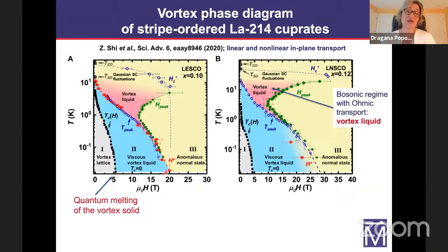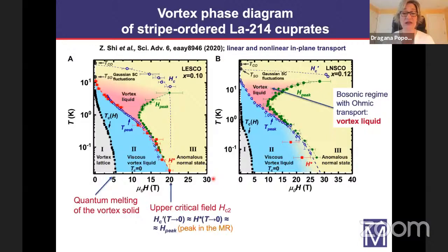So what we see here also is that all these different energy scales coincide, and it seems that this field here, 20 Tesla in this material, corresponds to the upper critical field. This is where superconductivity with vortices vanishes. We also looked at the magnetoresistance at high temperatures in a standard way, and these open dots represent the onset of Gaussian superconducting fluctuations, and they actually extrapolate in the zero temperature limit to the same field, supporting our conclusion that this is the upper critical field in these materials.